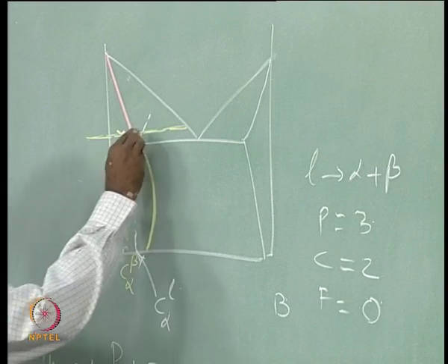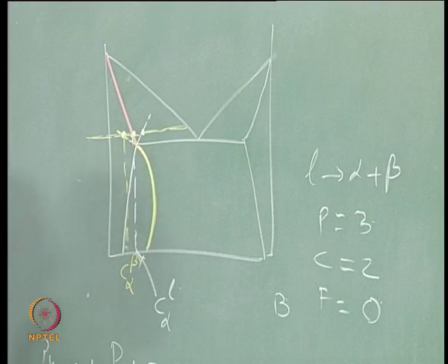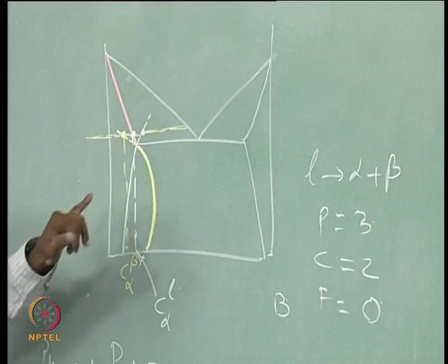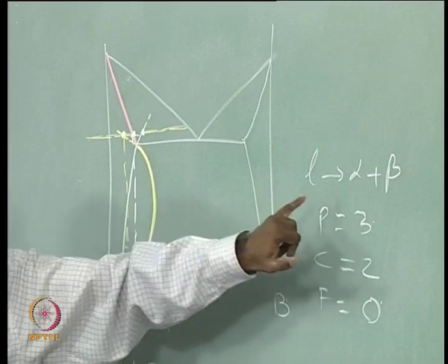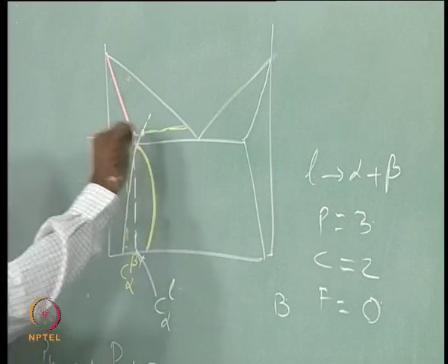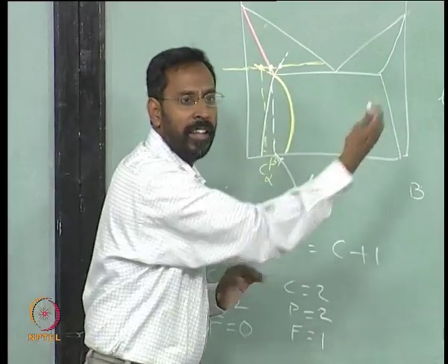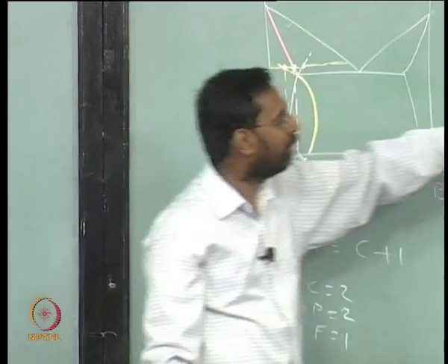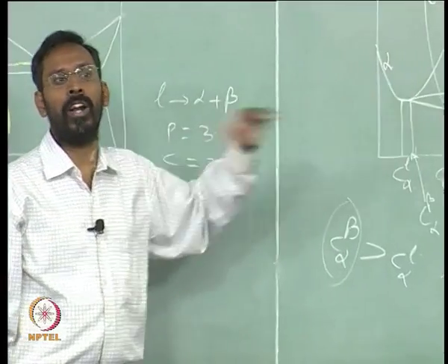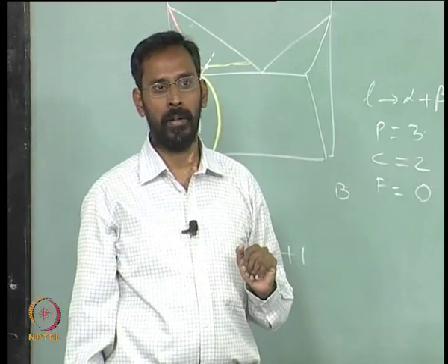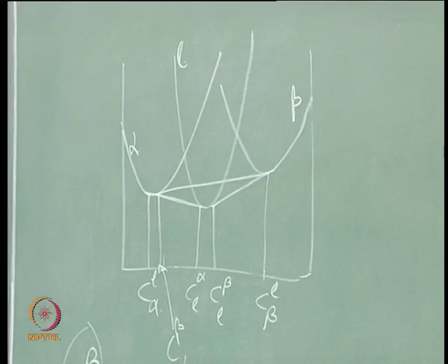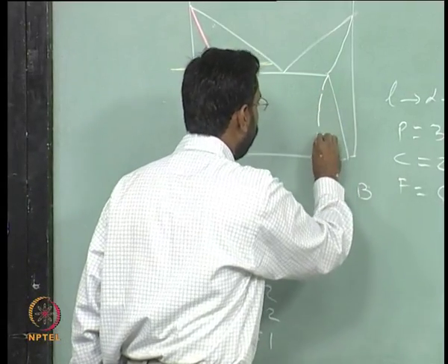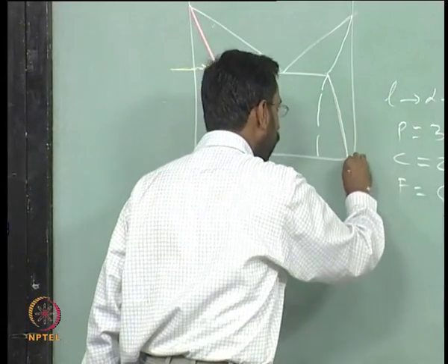I can clearly see that this particular composition now, which is nothing but the extrapolation of the alpha solvus, means this is the composition of alpha in equilibrium with beta. So, the composition of alpha in equilibrium with beta now is higher than the composition of alpha in equilibrium with liquid, and that satisfies the free energy composition diagram for that particular temperature. As a result, this kind of curve is not possible. So, you cannot draw a solvus line like this, you have to draw a solvus line like this, so that